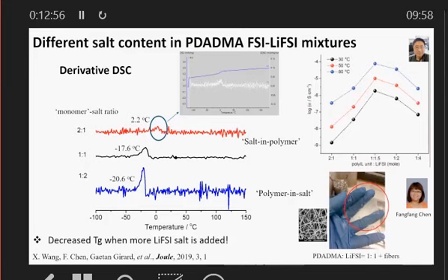And I'll show you that with some modelling that Dr. Fangfang Chen has done for us. As I said earlier on, these materials, I won't lie, are quite soft. And so in order for us to do a more robust characterization of materials in, say, a cell, we incorporate them into a PVDF spun mat, which is between 50 and 100 microns. And then we form these nice squares or self-standing membranes that we can do further testing on. But we are working towards, I'll show you at the end, making these freestanding without having to add anything else.